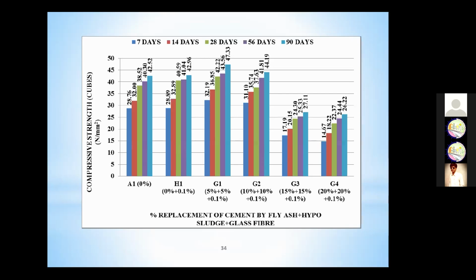And comparatively, at 28 days, A1 is 38.52, H1 with the glass fiber addition is 40.59, G1 is 42.22, and then G2 is 37.63. So 10% plus 0.1% glass fiber increases the strength. So it is beneficial regarding the compressive strength, and at a later stage, it is beneficial to the rigid pavement.